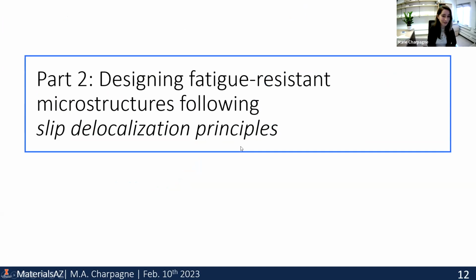Okay, so now that we know what we have to work on, well, we have first highlighted the linkage between the microstructure and the strain field that we can map in DIC. And we have highlighted that annealing twin boundaries are the weakest link in those microstructures. So by tweaking the microstructure, we're hopeful that we can get rid of very intense slip bands in the microstructure and hopefully increase the fatigue performance. So this is our new paradigm that we came up with that we call slip delocalization. And I'll explain a little bit what this is. But really the idea of this principle is how to design and process better materials so that we get rid of the weakest link in the microstructures.